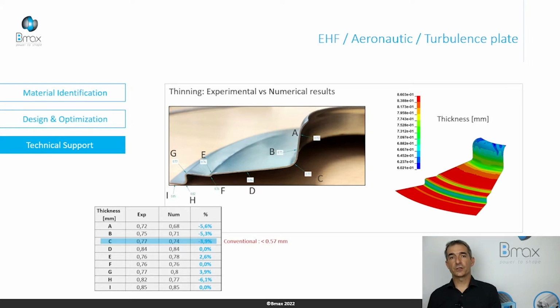We can pay attention to the third point. It's the radius, the most critical area for the conventional stamping process, where the thickness was around 0.57 millimeter. In our case, the final thickness is 0.77 millimeter. Remember, the initial thickness is 0.8 millimeter. So we have no thickness reduction in this area. So with EHF, we have no scrap, and all the parts are 100% compliant with the geometrical tolerance.